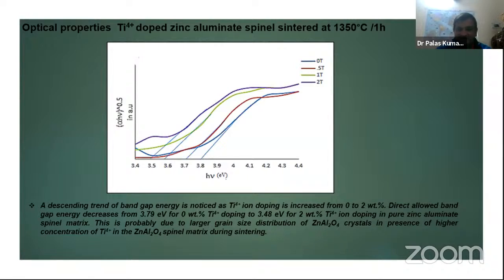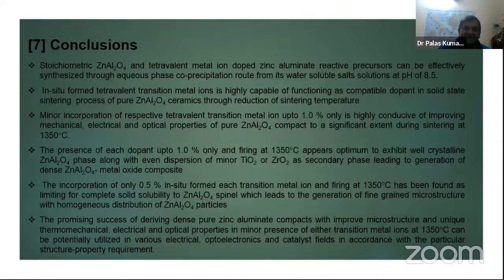So I'm coming to the interesting applications, how we can apply this in our practical field. So after this study, there are basically three major parts of intervention we can conclude. One, synthesis part, second, property, and third, application. So if we see the synthesis, it is clear that both the doped and undoped versions, with titanium and zirconia doping, can be effectively synthesized through the aqueous phase co-precipitation route, maintaining the pH.